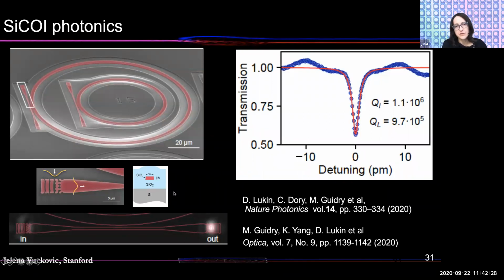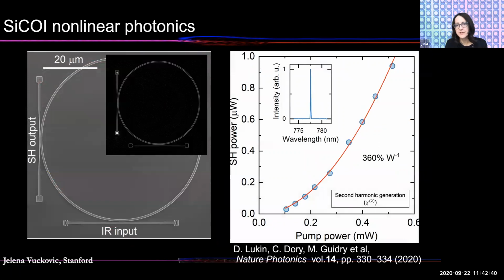And all of the structures that you see here are basically covered with oxide. So they're buried in oxide, like typical silicon on insulator structures. So they're not really suspended structures. I mentioned that silicon carbide has excellent second order nonlinearity. Last year, we first performed second harmonic generation experiments.